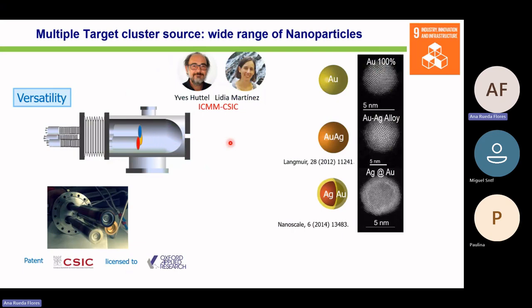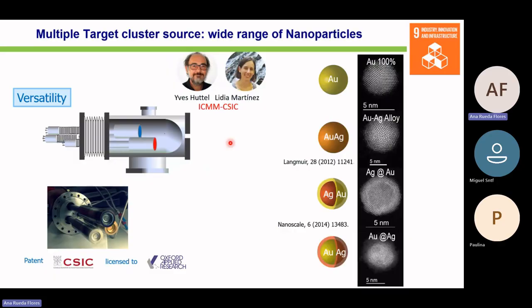We can retract the yellow and put in front the red. So we have the complementary core shell nanoparticle. And this is another difference compared to chemical synthesis, because with chemical synthesis, you can have only one of these core shell nanostructures. For instance, if you're using electrochemistry, these metals have different reduction potential, so only one of these core shell structures can be produced, because in electrochemistry, you work with in equilibrium conditions, whereas we are not limited by that in this physical method.